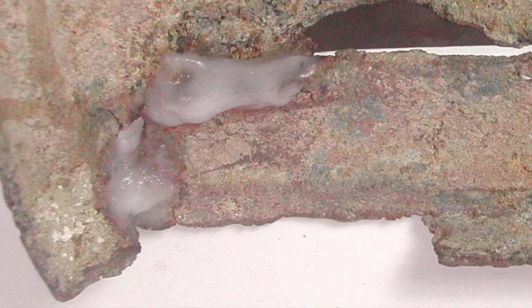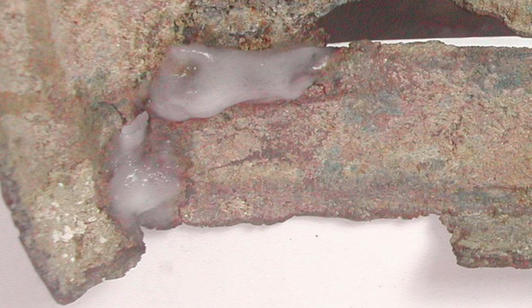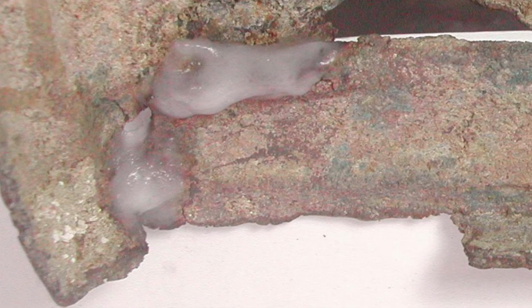After the disassembly, all fractures were cleaned with a highly volatile solvent to remove all remaining residues of the old resin. Next, the active copper chlorides in the surface had to be treated. The light green copper chlorides were removed mechanically using a scalpel and glass fiber brush under a microscope. Wearing protective clothing and a face mask, as these chlorides are potentially carcinogenic and can be transferred to unaffected copper areas. After the removal of the surface chloride corrosion, the area was degreased and treated with corrosion inhibitor.